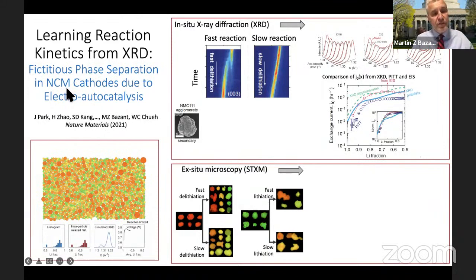And this material is nominally, or you might expect, much simpler than lithium iron phosphate. It's not a phase separating material. It's a so-called solid solution material. So lithium goes into this material and just diffuses freely. And that's known by a variety of methods. And yet, people had published a number of papers before our work giving evidence that there seemed to be, at high rates, some evidence of new thermodynamic phases appearing.